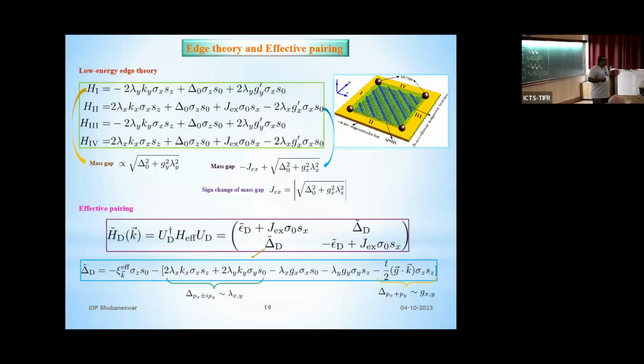And why these corner modes are appearing, we can have slightly more insight also from the edge picture. I can develop a theory starting from the bulk, and I can develop a low energy edge theory. Suppose you name these edges as 1, 2, 3, 4. If you look at edge 1 and edge 2, after deriving that, you can see the mass gap of edge 1 is proportional to this parameter. But for the mass gap of the second edge, there is a competition, and I can change its sign by varying the exchange. So there can be a sign change of the mass gap at the second edge, depending on this parameter.